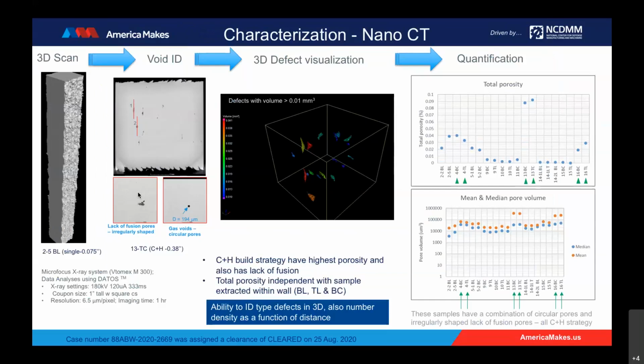What you can see in this chart here is a nano-CT evaluation from the left to the right. You start with a 3D scanning with the void identification, visualization, and quantification. We have kept the coupon thickness constant, just to make sure that we are looking at the same interaction volume. The resolution of this is about 6 microns per pixel, and it takes about an hour to image these. So they were really quick turnaround. It was very clear that the C+H, the contour plus hatch build strategy, showed the highest amount of porosities. So it was a clear indication and a powerful technique of nano-CT, where we could not only identify the type of defects, we could visualize the defects, get the number density as a function of distance from the surfaces, and also correlate that with the build strategy, which was, I think, a great insight. And realistically, for thin wall builds, you can do it in a non-destructive fashion also.